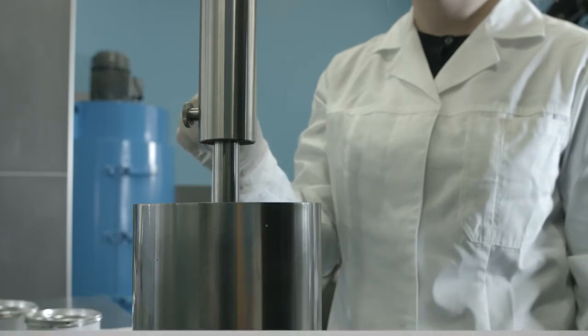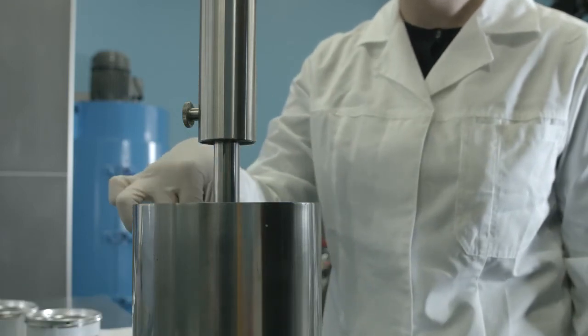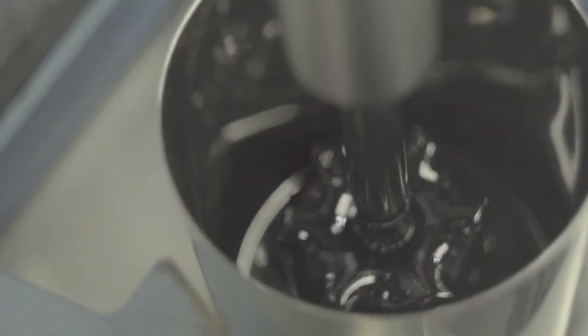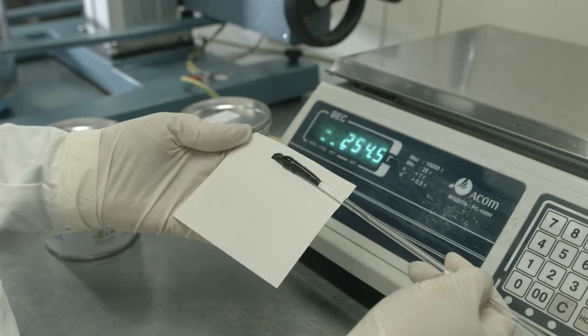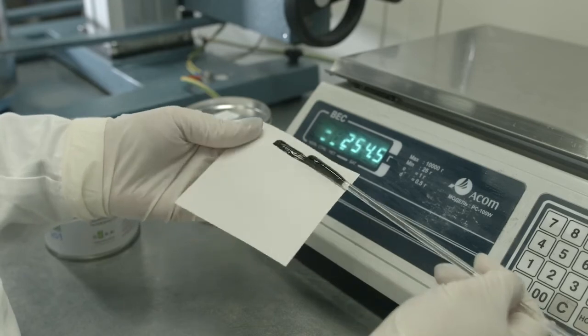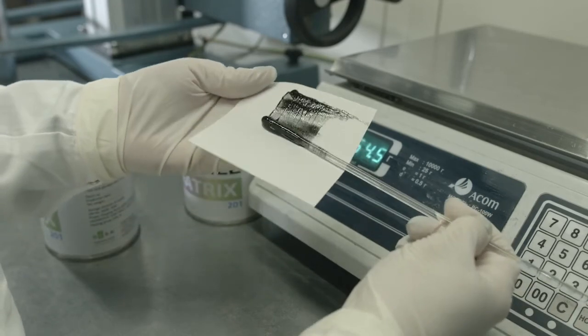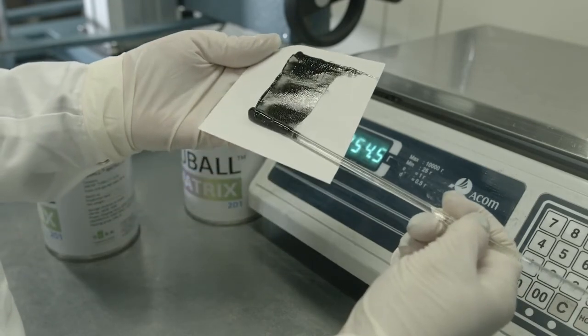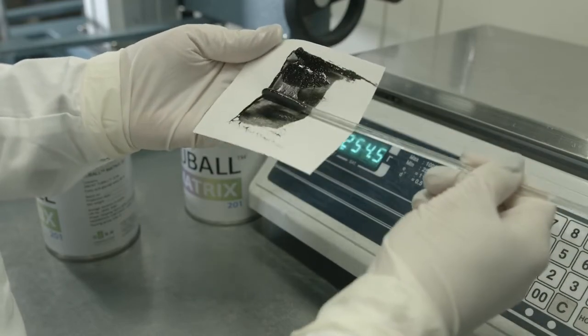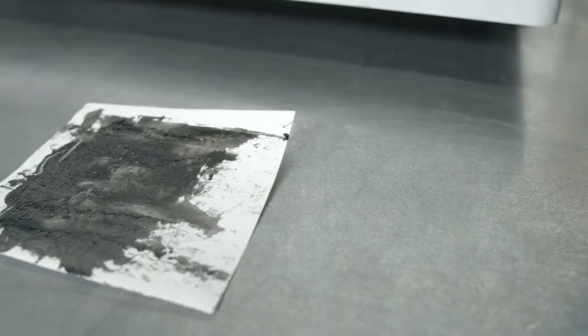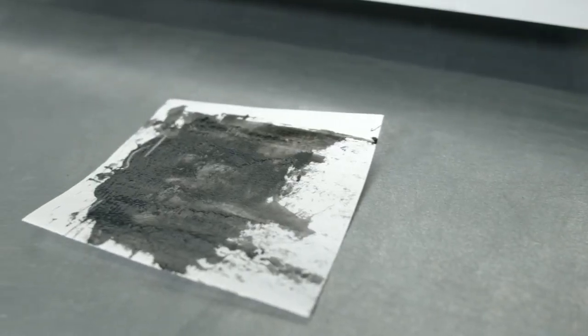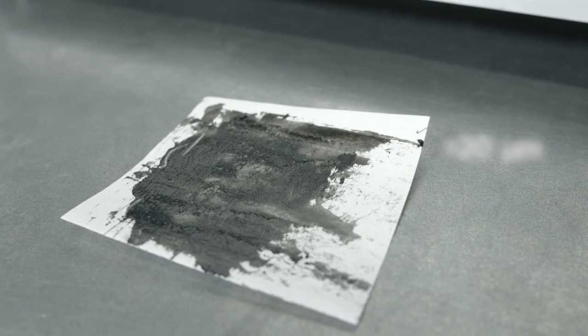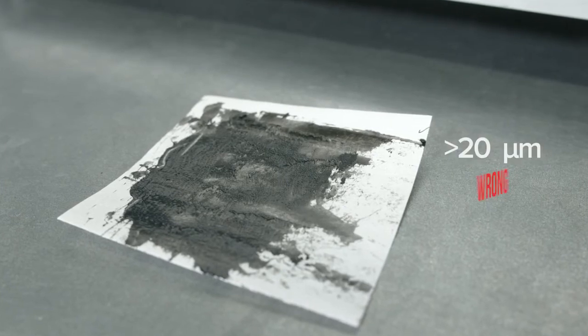The quickest and easiest method of examining the dispersion quality is to take dip samples with a glass or plastic stick and then to flatten the sample into a thin layer on a white sheet of paper. If non-uniformities are present, continue stirring until another sample shows that complete dispersion has been achieved.